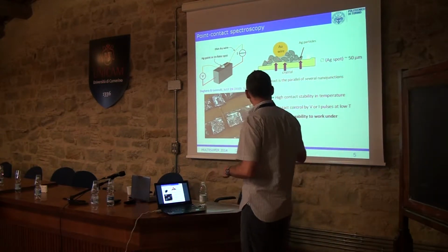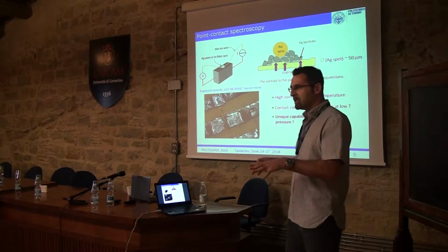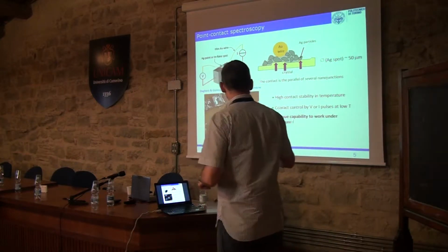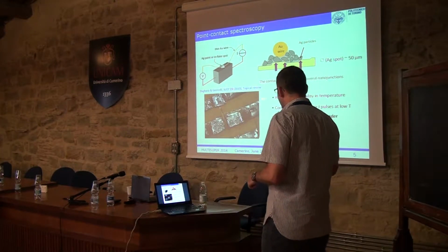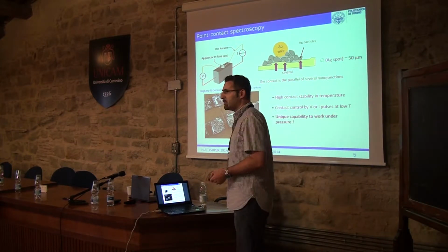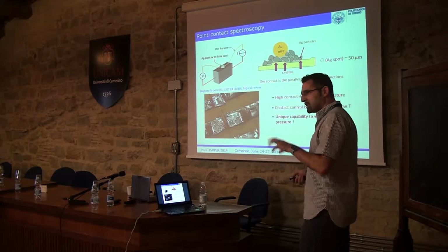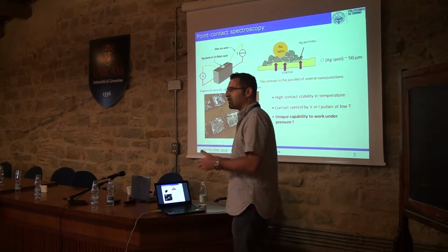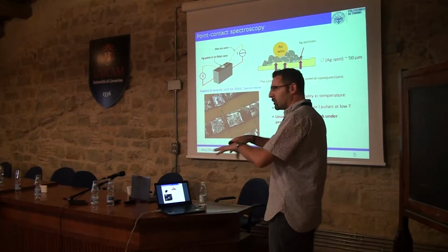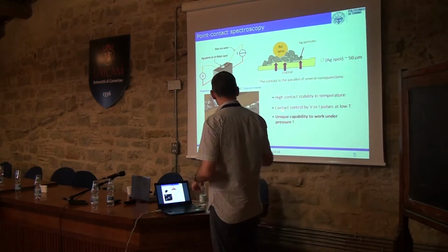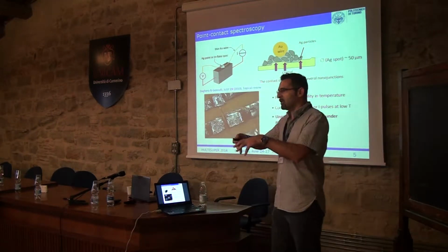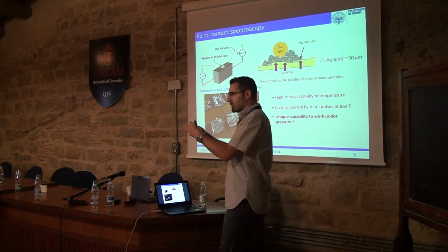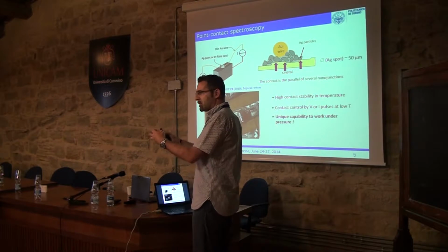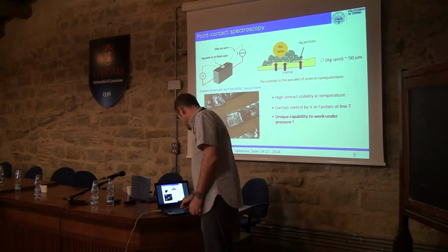So this is a sort of spatial average of the signal, and this setup allows high contact stability in temperature. It still allows control of the resistance of the contact by applying short voltage or current pulses that change the network of nanocontacts, and it also has the unique capability to be used when the sample is enclosed, for example in a pressure cell, which is essential in this case.